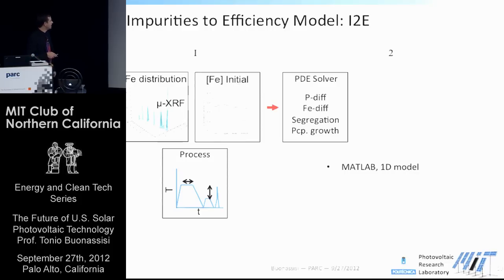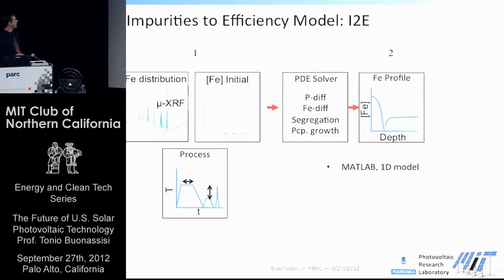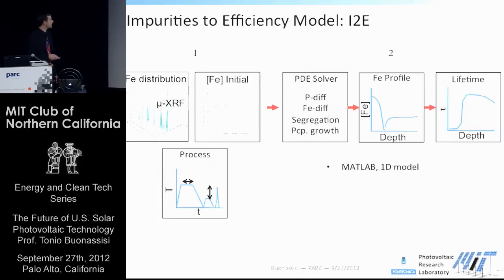separates charge. We can describe the diffusion of iron as well, using simple Fick's law, the segregation of iron into that phosphorus-rich layer, and the precipitate dissolution and growth. As we know, the precipitates will dissolve at higher temperatures and then grow as you begin cooling back down. We can solve this using MATLAB. We can determine, based on this PDE solver, what the final distribution of the defects will be throughout the thickness of the wafer. And from that, we can determine the electrical performance of the solar cell.